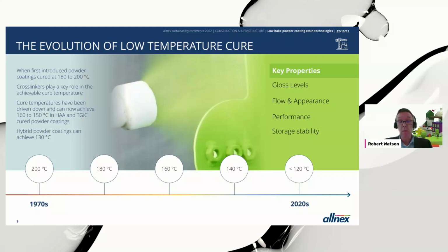European market. But what we can say is that within the constraints of the curing chemistry that's imposed by the crosslinker, the resin industry has done a great job of designing resins that can cure at lower temperatures and really pushing the envelope of what's possible within the chemistry. So with HAA, we can get down to 160 degrees. With TGIC, another important crosslinker, triglycidyl isocyanurate, we can get down to 150, even 140. And when we cross-link a polyester with an epoxy resin, the so-called hybrid powder coatings, we can get down to 130. But as we move through the generations and we come to this particular decade, 2020 and beyond, we're looking to get powder coatings below 120 degrees centigrade when we can really start to penetrate these alternative substrates.